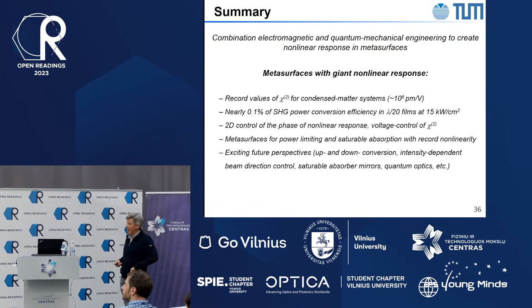And in the expressions for the nonlinear frequency conversion, this term chi2 comes squared. So we benefit a lot. This allows us to produce significant amounts of second harmonic generation in deeply sub-wavelength films using light intensities that are comparable to the light intensity of this laser pointer.